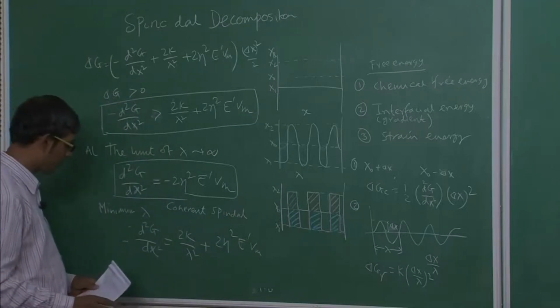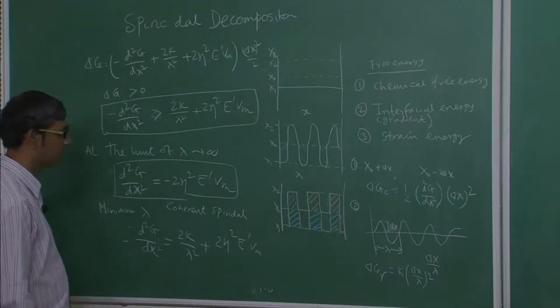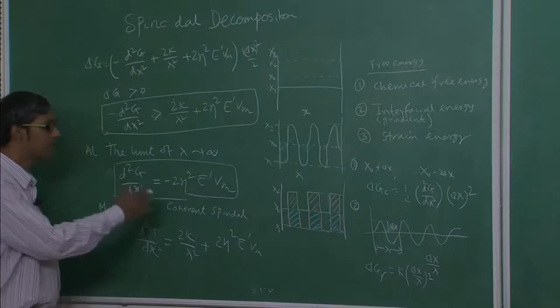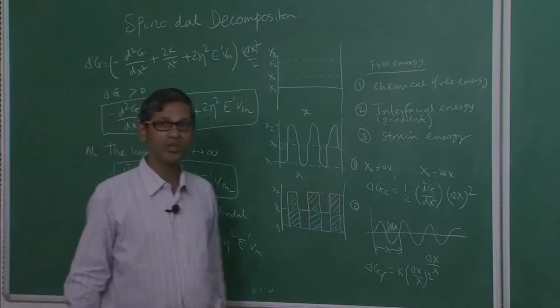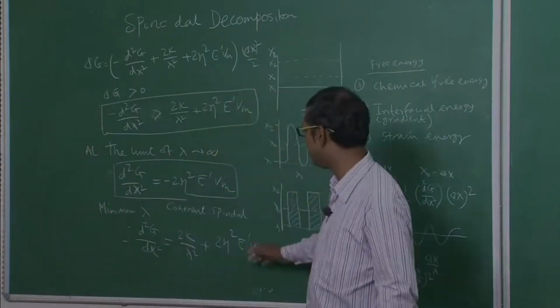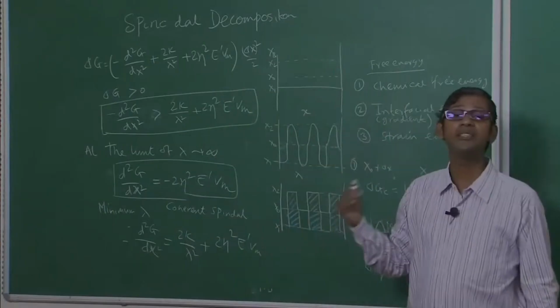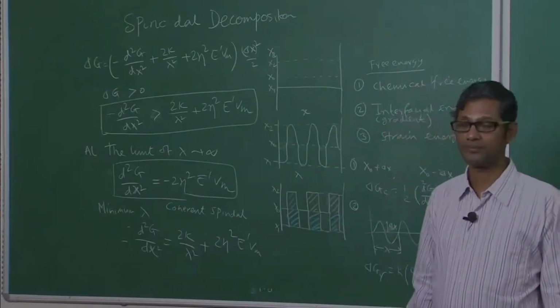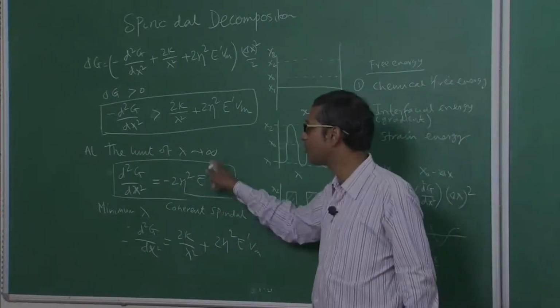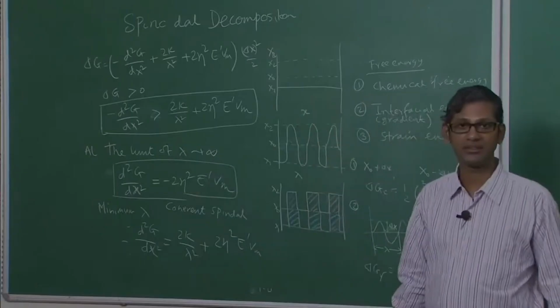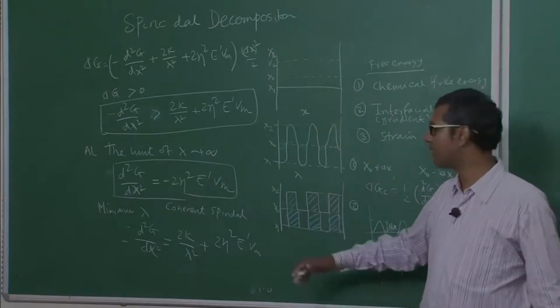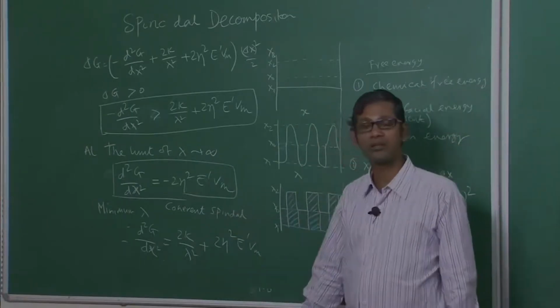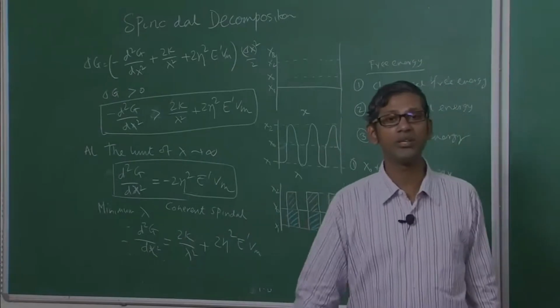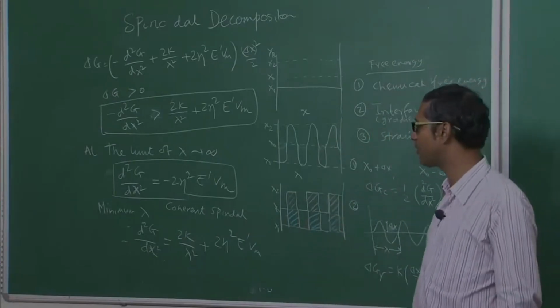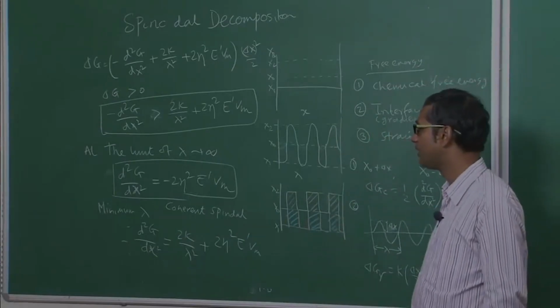Or we can say coherent miscibility gap. Okay. So this miscibility gap, which I will show you in the next lecture, lies within the chemical spinodal, because this corresponds to lambda infinity. When you have very large lambda, you have a coherent spinodal. That means the regions are actually completely coherent. That is why it is called a coherent spinodal.